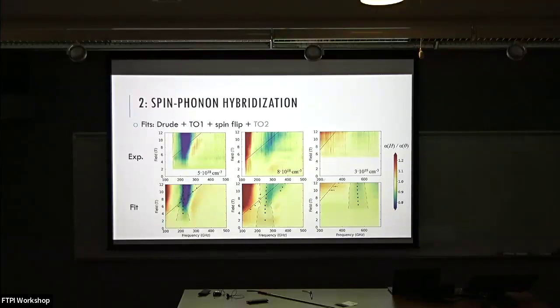What we were able to do is do these fits. So these are just simple heuristic fits of a Drude part, that's the red blob, 2 TO modes, and the spin flip mode, which according to this theory, when you're close to the anti-crossing point, the spin flip will have some phonon character. So there's going to be a phonon weight associated with it. So if you do these fits, you can pretty much reproduce what is seen.